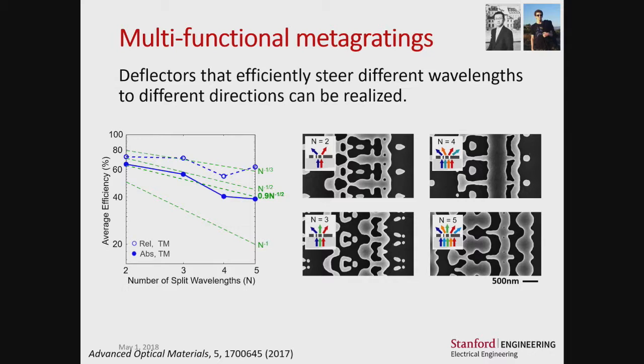Here we are taking in different wavelengths and splitting them to different diffraction orders as a function of wavelength. These are top view SEMs of these devices. Here we can see that as we plot the average efficiency of wavelength splitting per device as a function of the number of wavelengths, these efficiencies scale as 1 over the square root of n. These are experimental values. This type of scaling is certainly quite a bit better than the typical 1 over n scaling that is typical of conventional devices.